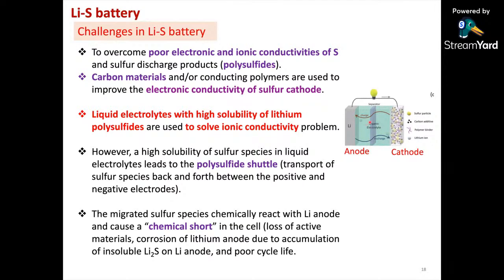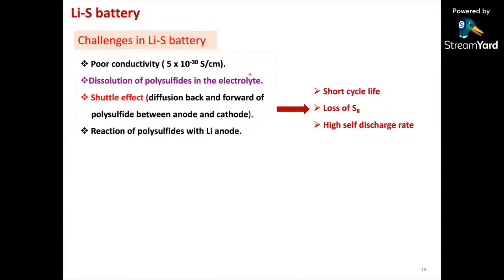But because of the dissolution of these polysulfides in these electrolytes, the polysulfide shuttle also occurs. That means that these polysulfides will come to the lithium anode, and you tend to get a chemical short. That means loss of active sulfur and corrosion of your lithium anode, because of the accumulation of Li2S at the lithium anode. So these are the challenges: poor conductivity of sulfur, dissolution of polysulfides in the electrolytes, the shuttle effect, and finally the reaction of polysulfides with the lithium anode.